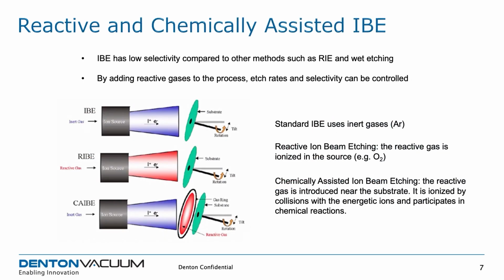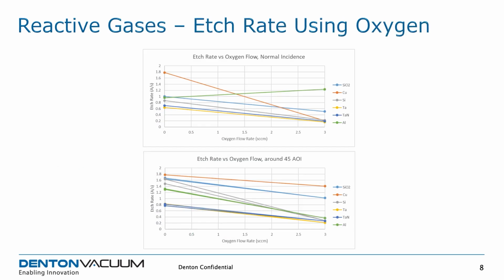So on the prior slide, I showed that you can control the selectivity just by changing the angle, but sometimes that's not enough depending on what material you're using. So this machine is fully capable of using chlorinated gases and fluorinated gases and oxygen. You can put it through the source or you can just introduce it to the chamber, and it comes standard with 6 MFCs. So there's a lot of flexibility in what kind of gases you want to use. Here is some data which shows the effect of adding just a little bit of oxygen to what is our normal argon etch process. So you can see that it dramatically affects the etch rate for certain materials, like copper dropped significantly, whereas for other materials, it either dropped less or even went up in the case of aluminum.